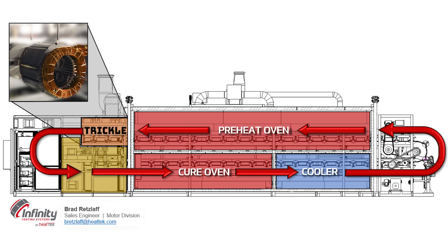Once preheated, the stator exits the oven and enters the trickle area. This is a non-heated zone. The ProPreg E240 is dispensed precisely. The dispense rate is determined by how fast the windings accept the resin. Typical flow rates are in the 0.5 grams to 5 grams per minute range on rectangular PEEK-coated wire used in hairpin designs. There are multiple dispense positions, typically 3 to 6 index positions where the ProPreg E240 will be dispensed.